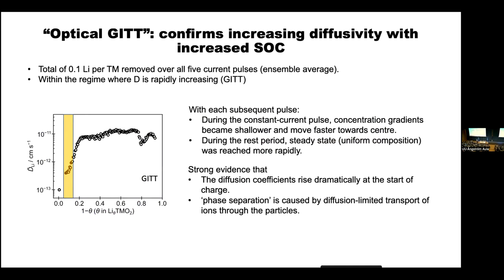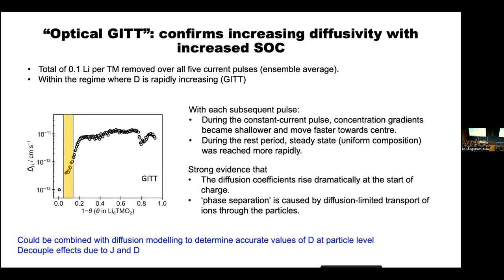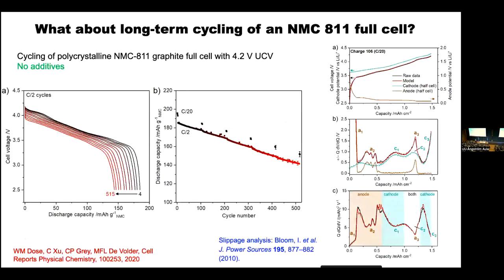So this is the regime we're getting, and this is the comparison with GITT. What we want to do now is to use this to try and explore whether there are different diffusion coefficients at different particles and try and decouple the effects from how fast the ions get into the material, J, and the diffusion coefficient. Okay, so what about long-term cycling in the full cell?